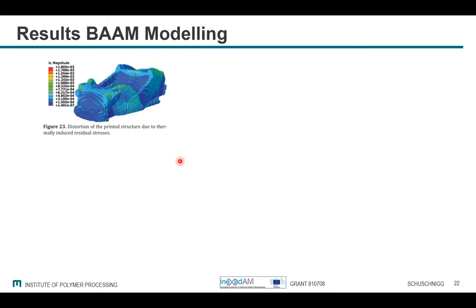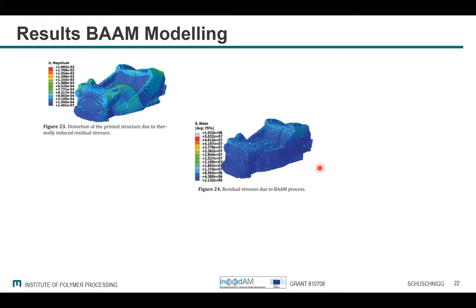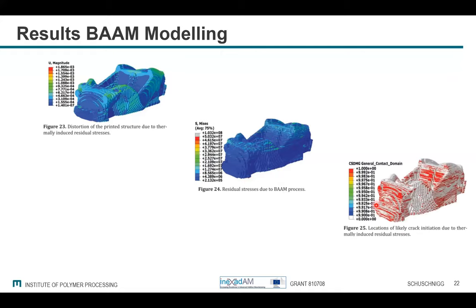And then I have these residual stresses. These residual stresses lead to the damaging of the different layers. And you can see here where they say in these areas the possibilities for cracks are higher. They also saw that directly at the car itself, in these areas here in the front fender, for example, they had quite thin sections. And in these sections, the cracks propagated mostly.